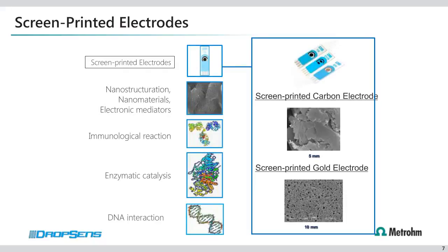As it was explained before, screen-printed electrodes are just transducers of the chemical event. The working electrode can be of different materials: carbon, gold, platinum, bismuth, ITO, PEDOT for transparent electrodes, and also including electronic mediators. On the slide, we see pictures of the surface of carbon and gold working electrodes.